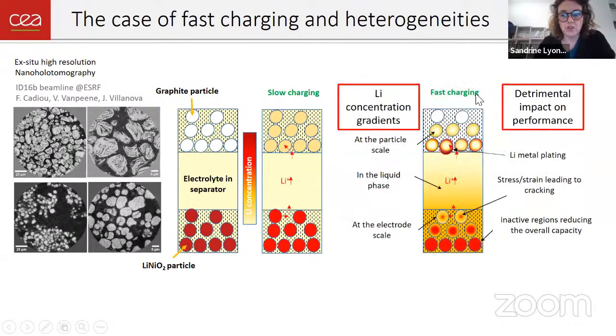But as soon as you do fast charging, you're expecting a lot of concentration gradients of lithium across the solid phases and also the liquid phase, and at all scales, at the scale of particles, but also at the scale of the electrode. And you might have different phenomena like lithium metal plating, or a lot of stress and strain in the particles causing some cracks, and also some regions that get disconnected and inactive. And all these phenomena that might happen when you fast charge your battery are completely detrimental to the performance. So you really need to understand them.